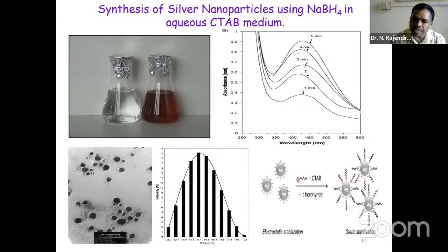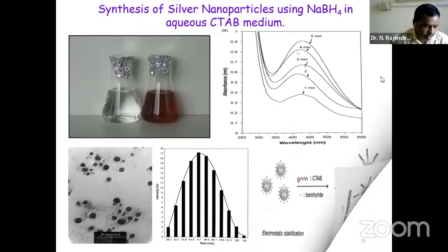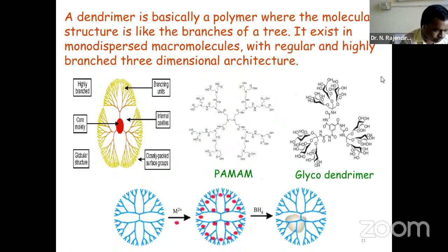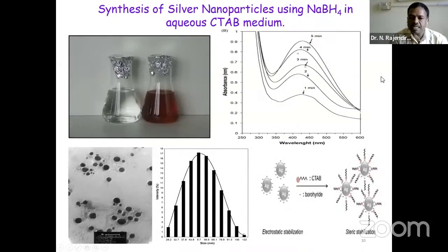After the preparation, we need to confirm the nanoparticle synthesis by using UV-visible spectroscopy, where this is the surface plasmon resonance. At different time intervals, as the reaction proceeds, the SPR band around 420 nanometer is increasing. That is one of the characteristic peaks for silver nanoparticles.